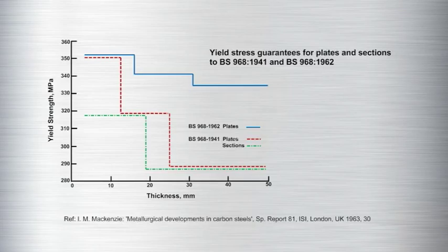and manganese contents. Unfortunately, even though I used hot rolling techniques in Colvilles to vary the grain size, I discovered at that time that all the niobium-treated steel samples were much finer grained than the non-niobium samples. I failed to recognize that niobium influenced the rate of recrystallization of austenite. So I missed that. But that fact was discovered here in Sheffield by Jim Irvine and his co-workers, that niobium had a very powerful effect on the rate of recrystallization of austenite during hot rolling. This led to the development of control rolling techniques, which allowed the production of high-strength, tough plate steels mainly used for pipelines, which benefited the oil and gas industry.